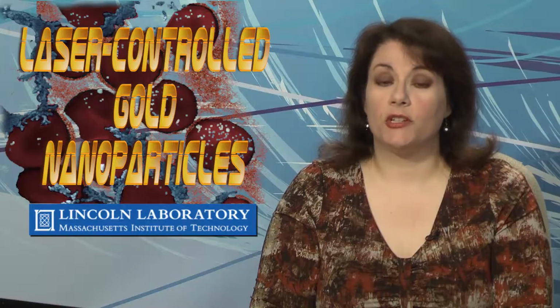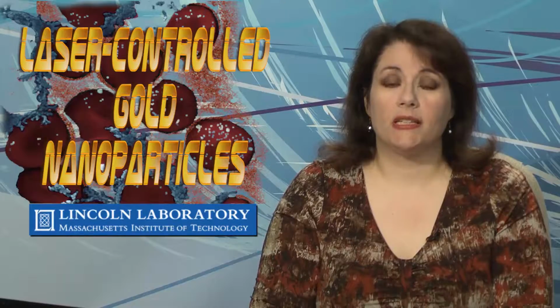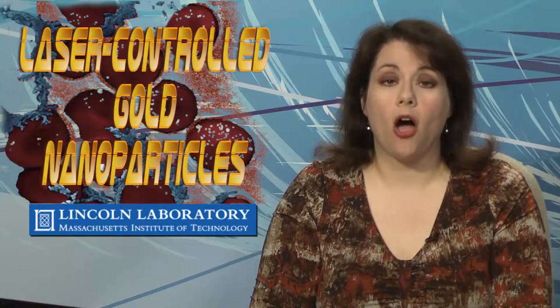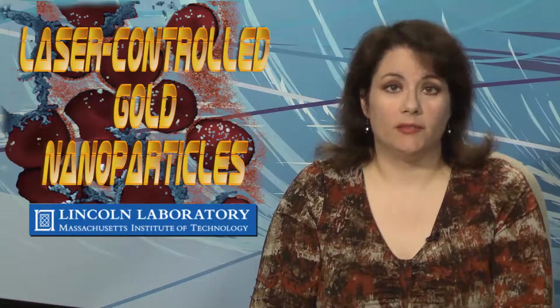When the nanorods are exposed to IR light, the electrons within the gold become excited and generate so much heat that they melt slightly, releasing the DNA. The process was tested on blood donated to hospitals, and the particles successfully turned clotting off and on in all samples. The research appeared in PLOS One.